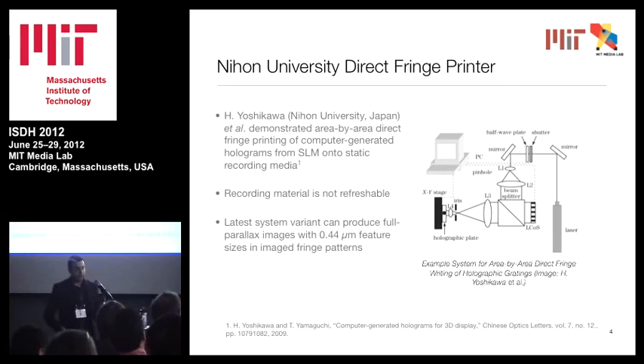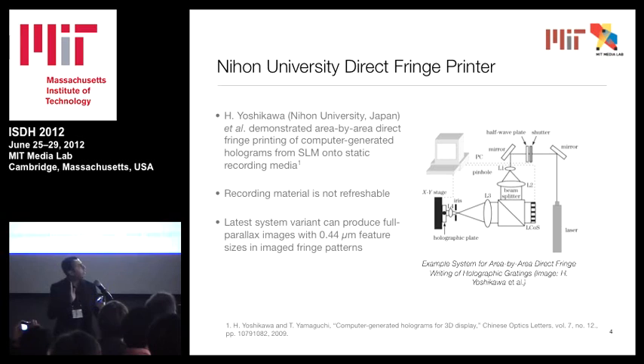Just side-stepping a little bit, I'm going to talk about some of Hiroshi Yoshikawa's work at Nihon University. They've developed, over the past five or six years, a direct fringe printer which images parts of a large computer-generated hologram in an area-by-area approach onto a static recording material. The material is static, so it's not dynamic, but they've achieved feature sizes in the image of 0.44 microns.